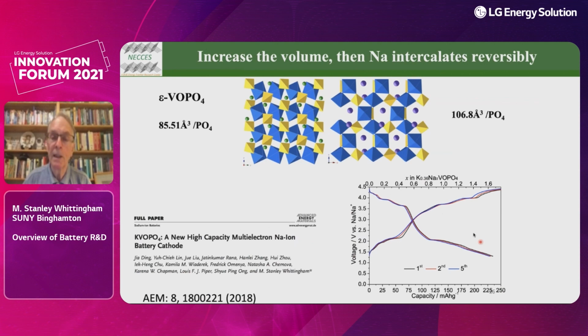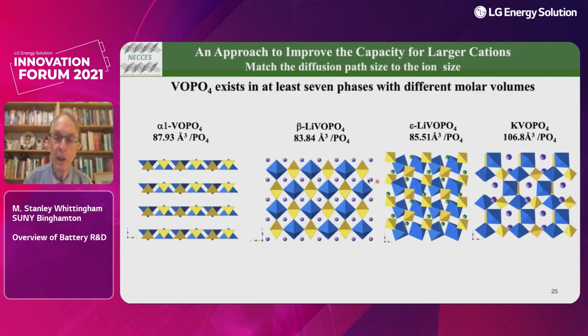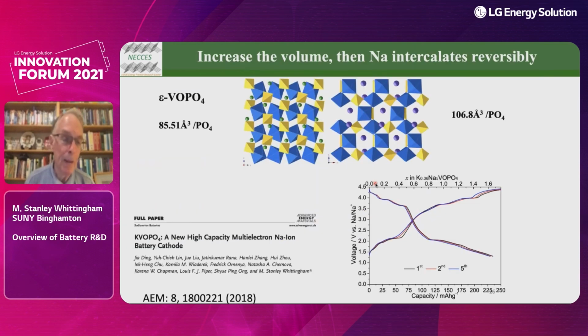So this is a very interesting structure. We're hoping that we can, in fact, enhance it so we can make these two materials react reversibly and be used and have a higher energy density than the simple lithium iron phosphate or lithium manganese phosphate. And we published this work about 3 years ago.